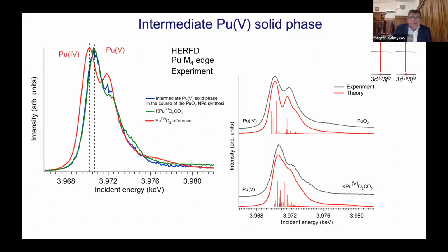That is quite surprising, because plutonium-5 is not very stable. It disproportionates to plutonium-6 and plutonium-4, and very few plutonium-5 solid phases are known. So by again using high energy resolution fluorescence detection at the M4 edge of plutonium and comparing the spectrum with the references, we can see that in the intermediate phase we don't see plutonium-4, and this is definitely plutonium-5 that we have.